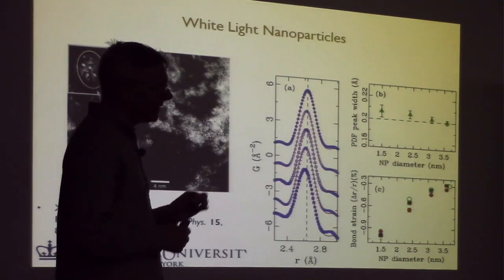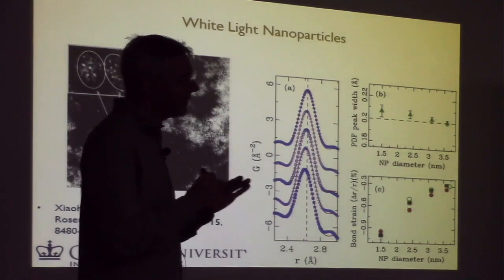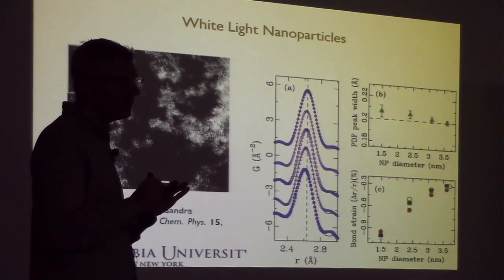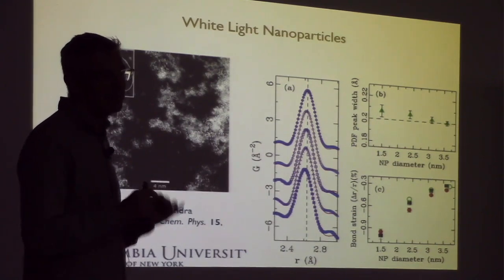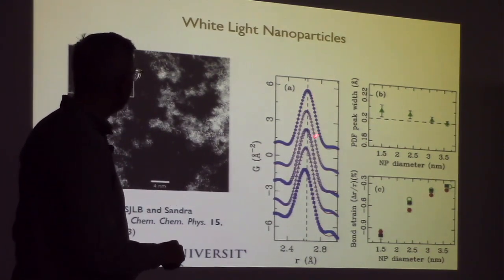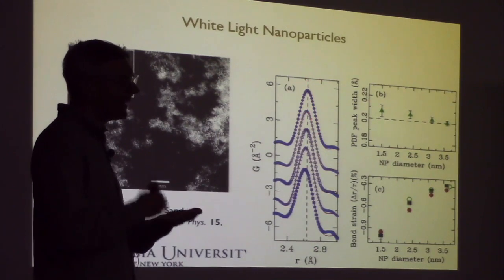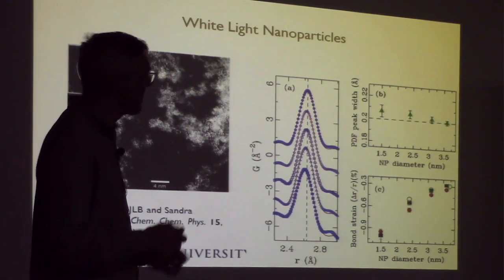And interestingly, these are tiny little 2 and 3 nanometer diameter nanoparticles, and we can measure strain. And what we do is, this peak here is the first peak in the PDF, it's the cadmium to selenium bond length.